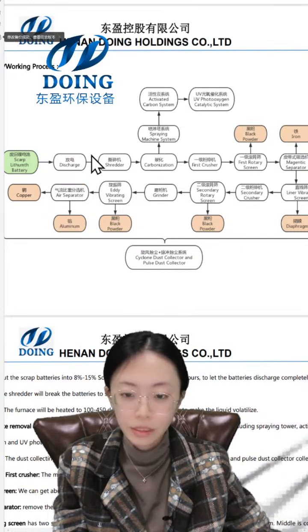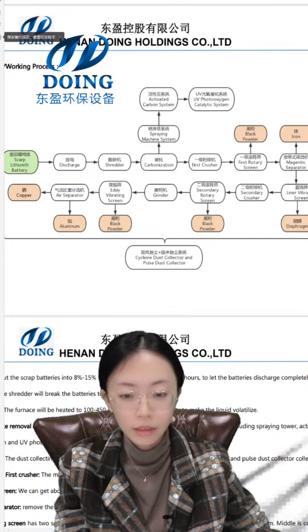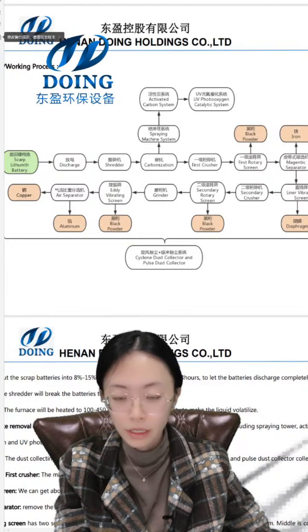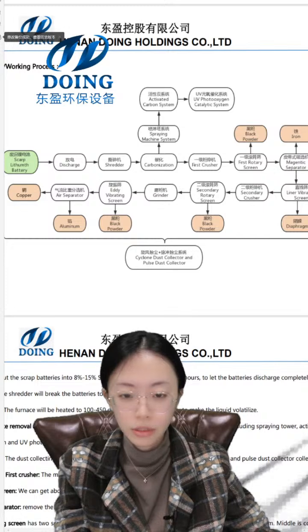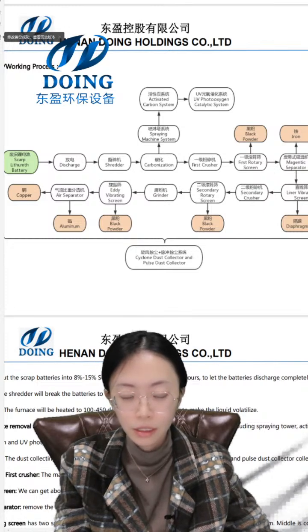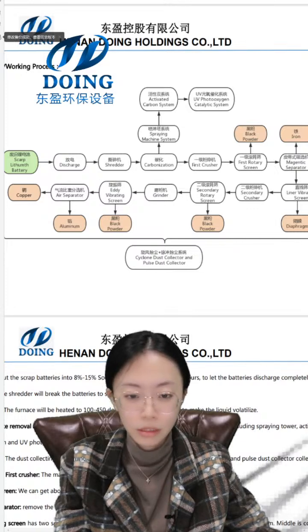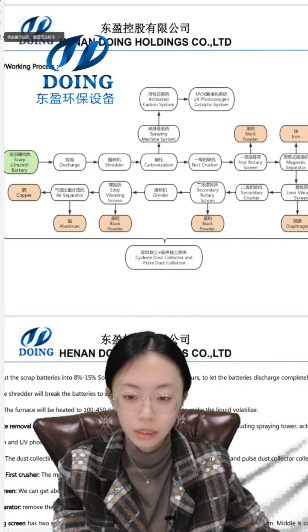This is the pre-process. We put the scrap lithium battery into a sodium chloride solution of 8 to 15% concentration to soak for 2 or 3 days, so that the positive and negative terminals of the lithium battery are short-circuited, and we can have the safe processing later. You can choose natural drying or a drying machine to dry your raw materials. If you choose natural drying, you need a soaking pool or barrel for the discharging, with industrial salt and water inside.